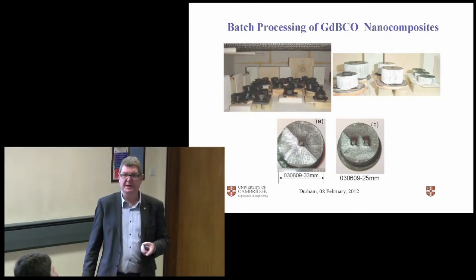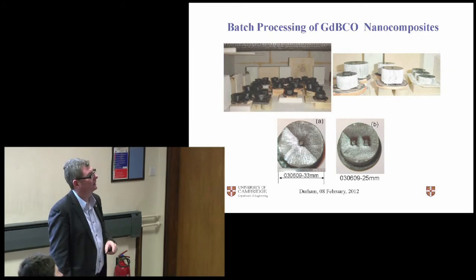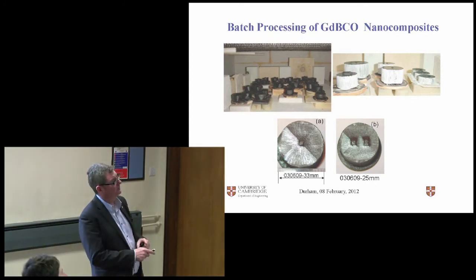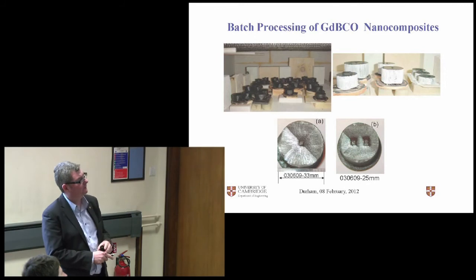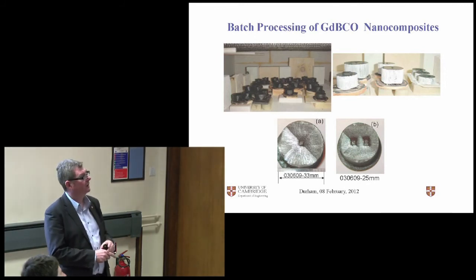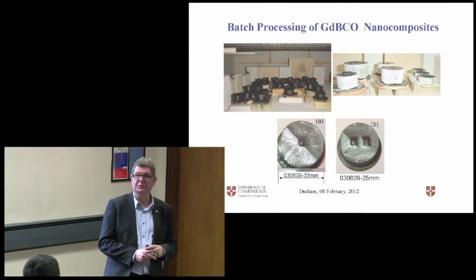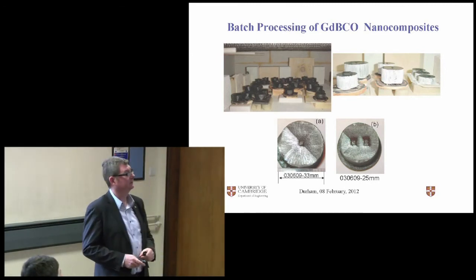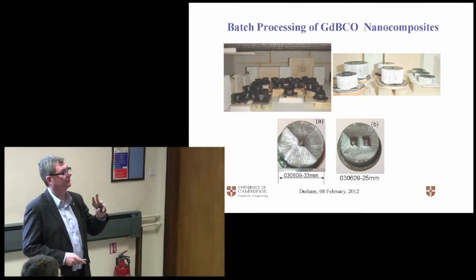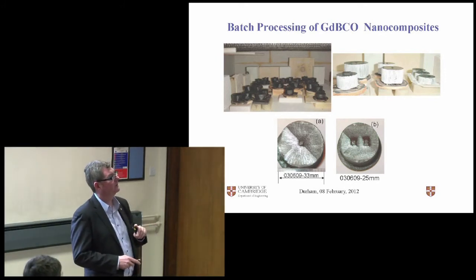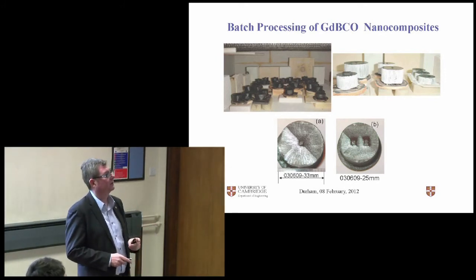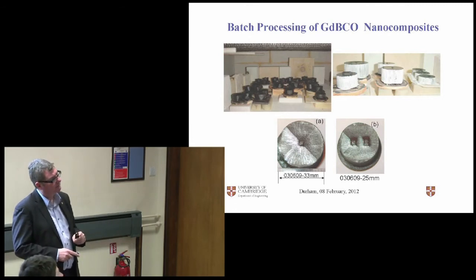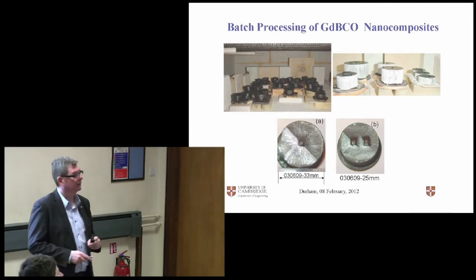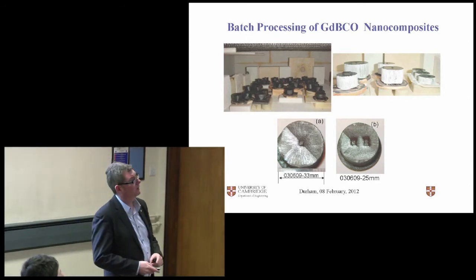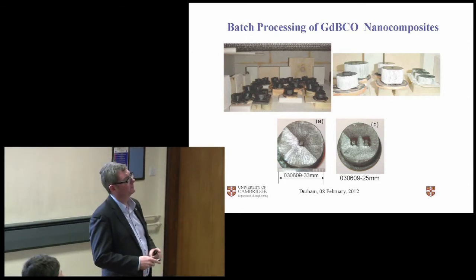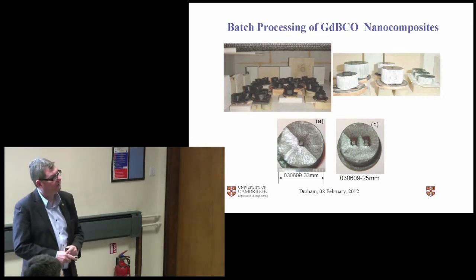The process we have enables batch processing, so we can make any number of materials. So this is our chamber furnace. It looks pretty untidy, but we can make 20 samples in one go. There's no way you can do this if you're using a tube furnace with a controlled atmosphere. And if you're using multiseeding, hot seeding, I've got absolutely no idea how you tackle this. But we've made 20 samples of gadolinium barium copper oxide. You do get a slight variation in performance of samples around the side, but they're much better than anything we can make with YBCO anyway. So this is the basis of potential commercial application.